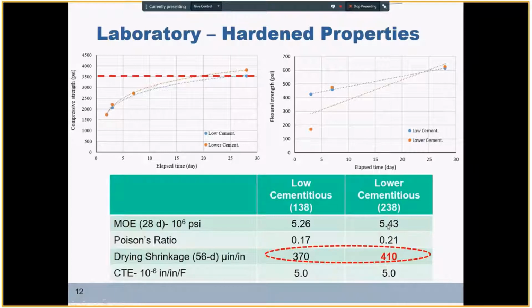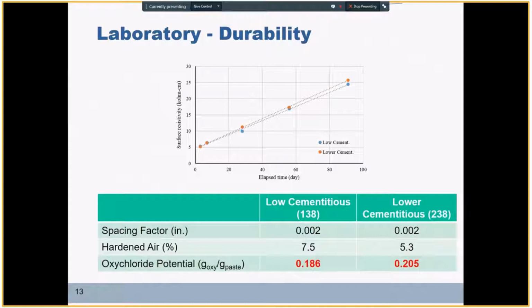There was a slightly higher modulus of elasticity with lower cementitious material, which can be because of a higher amount of aggregate in that mixture, and a slightly higher shrinkage value at 56 days. Both numbers are low, but with reduced cementitious material we would expect a lower shrinkage value. However, because of the increase in water-cementitious materials ratio, shown earlier in microwave test results, we had a slightly higher shrinkage value here. But again, both are very low, very good numbers. Also comparable CTE data for both concrete mixtures, which could affect deformations under temperature variations.